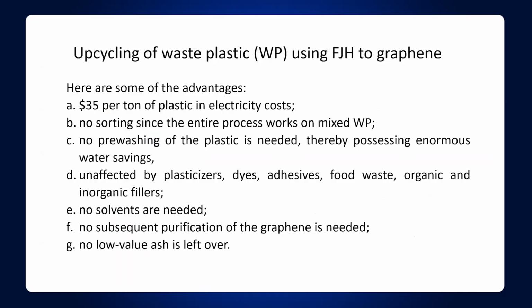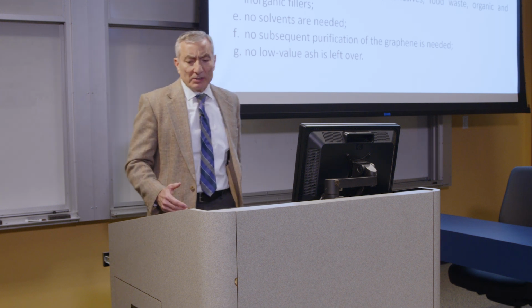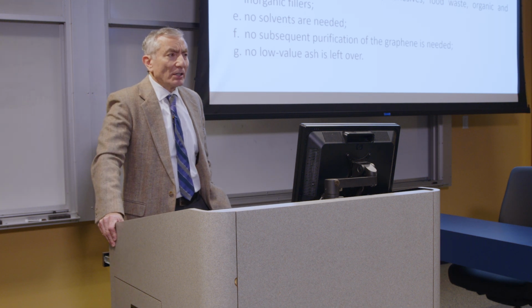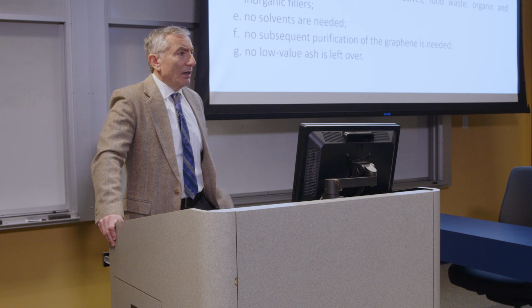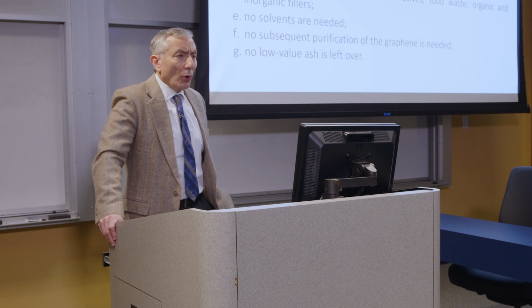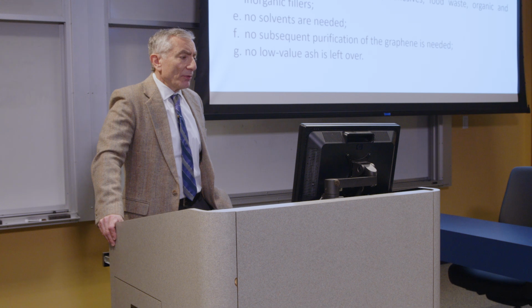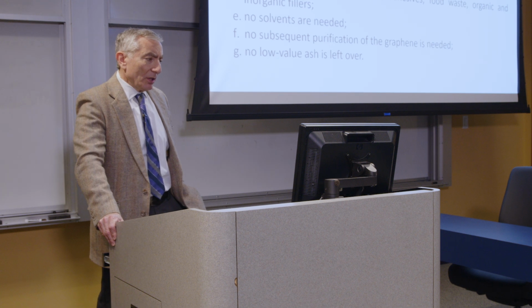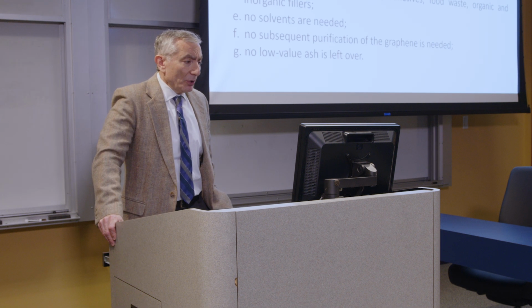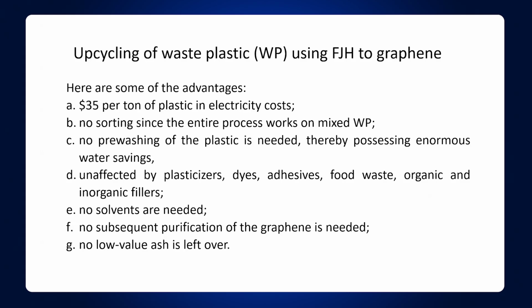It's carbon black. So what about upcycling of plastic waste using flash graphene? Here are some of the advantages. It's about $35 per ton of plastic that you have to put electricity in. If you're dealing with a different type of carbon, something that's much higher in carbon content, like say coal or petroleum coke, then it's about $30 a ton. Plastic, you have to put a little more energy, but that's not much. $35 per ton in electricity.